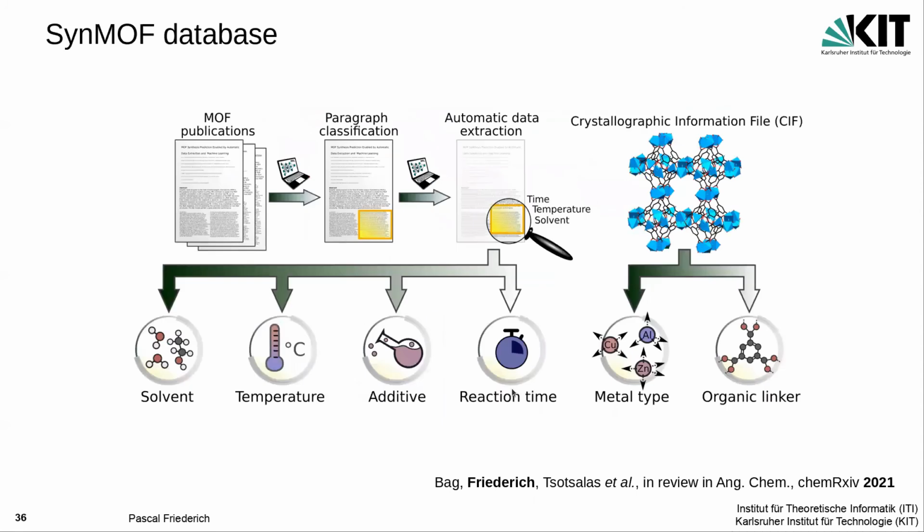We created a so-called SynMOF database where a postdoc of Manuel Tsotsalas' group was developing an algorithm to automatically extract MOF synthesis recipes from the literature. We were extracting what is the solvent, what is the temperature, the additive, and the reaction time. And then we automatically extracted also information about the molecular structure, the metal type, organic linker, and so on, from the CIF files, the CIF structure files, which are available for all of these MOFs. And this is all included in the database.